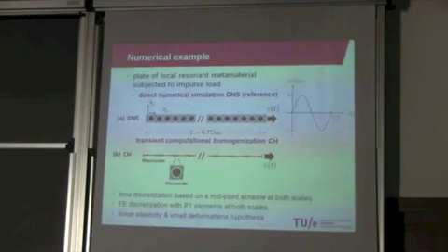Now, for the computational homogenization on the macro scale, I have this sort of 1.5D element, so that's a one-dimensional element with two degrees of freedom, horizontal and vertical. And on the micro scale, I have this microstructure with the materials and properties as in that material of Liu. So I have epoxy matrix, lead inclusion, and the rubber coating.